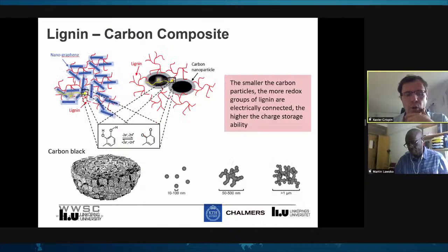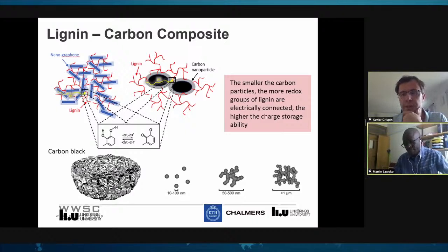If you have a very low fraction in carbon blacks and others, you have a very large surface area, basically 1,000 square meters per gram, and these are very tiny pores. If you find ways to bring the lignin inside, that could also be interesting. The challenge is that they must be kept insoluble. If you are in contact with an electrolyte, and you have the right electrolyte that does not dissolve it back, it's okay. Otherwise, you need to find in addition a strategy for cross-linking them or connecting them to the carbon. This is also possible, but there is a lot of chemistry and interesting tracks there. Definitely.